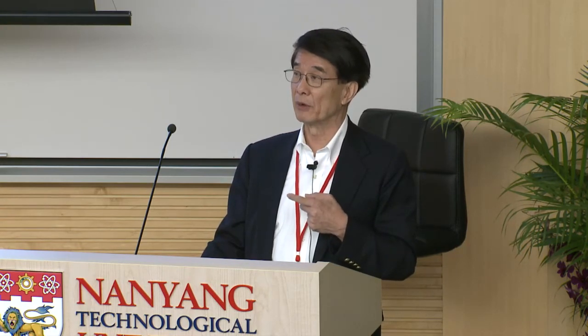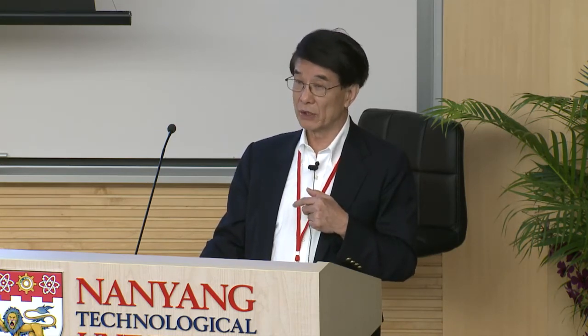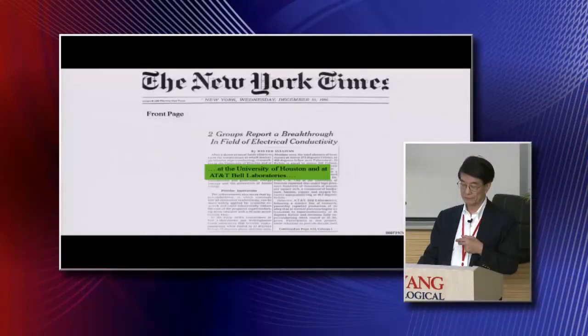That includes, for example, replacing the barium by strontium and calcium. At the beginning, with strontium, TC goes up. That was very nice, but unfortunately, when we replaced it with the smaller element calcium, TC goes back down. So then we also looked into the other element, lanthanum. We can replace it with some smaller trivalent elements. Of course, usually those are rare earth materials. They are all magnetic, and we thought magnetism usually works against superconductivity. So at the time, we proposed to use yttrium and lutetium and so on.